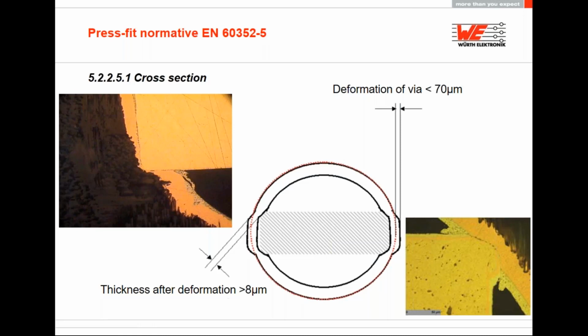And so a square cross section of the press fit technology carves into the copper traces. So the corners carve into the copper traces, making the connection and not the entire wall, like with a rectangle, let's say. Tin helps lubricate and protect against oxidation when the pins are pressed into the via. So tin plays an important role in this process. And as you can see with the rectangle shape, there would be more deformation on the PCB. That may not be desirable for your application because it may deform maybe some components around it, and you might not want that in your application. With the press fit technology, we can just carve through the corners and there's minimal deformation.